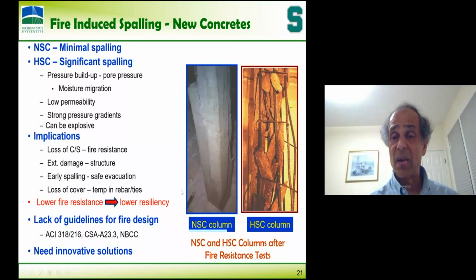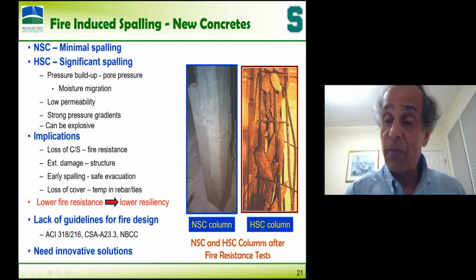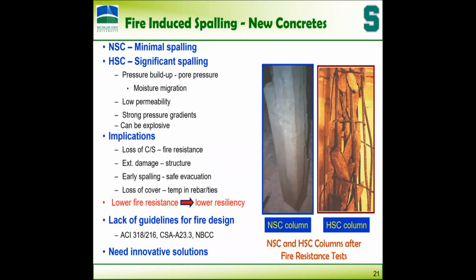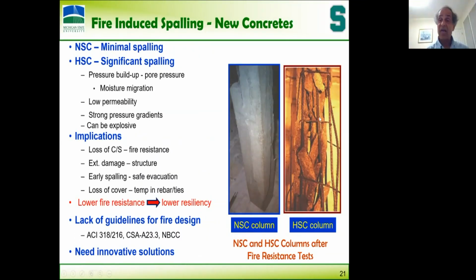Look at a concrete column, 6 hours in a fire, which I tested, nothing happened, 16-inch column. This is a typical column used in Chicago. And look at the high-strength concrete column, 19 minutes. This was done for Portland Cement Association and Construction Technology Laboratories. I did these tests at NRC, about 15 columns were tested for them in addition to a number of other things. So we developed a lot of guidelines.